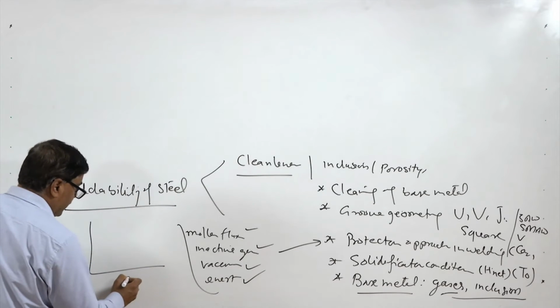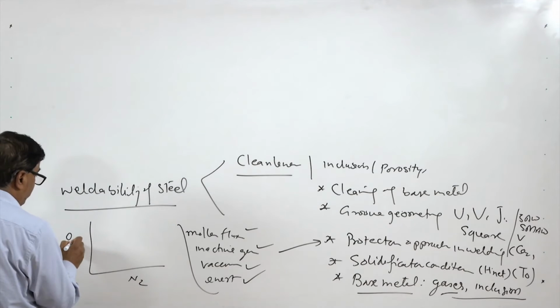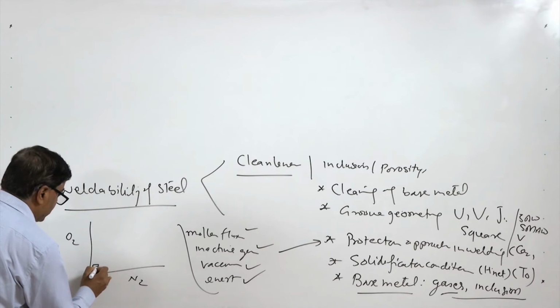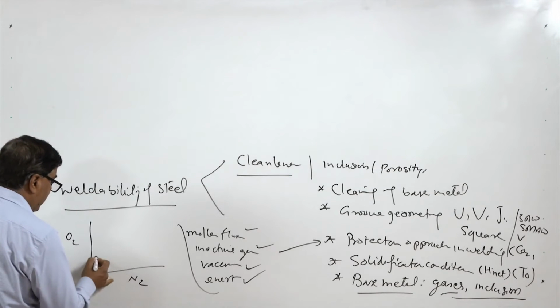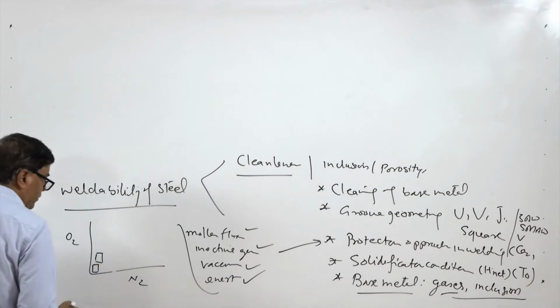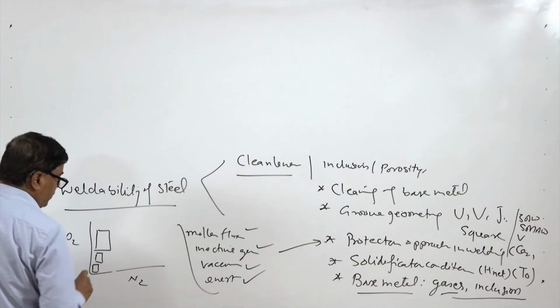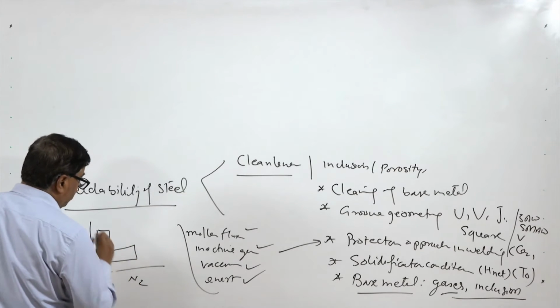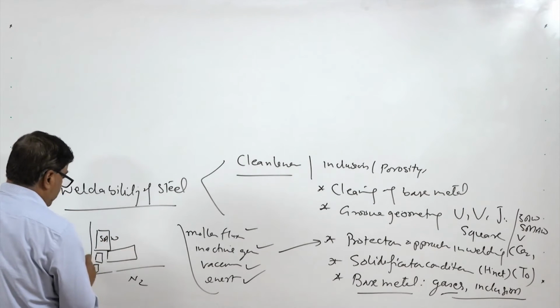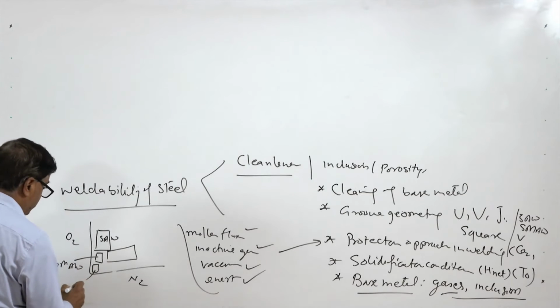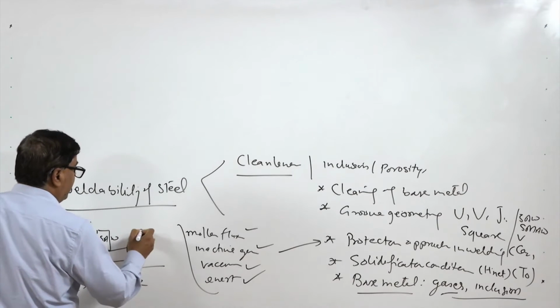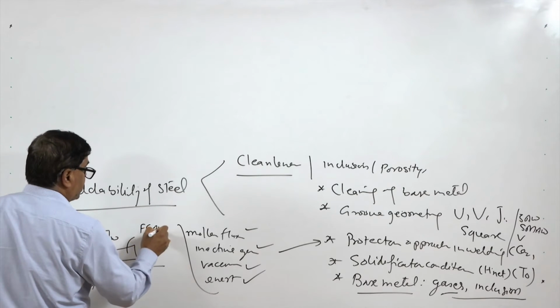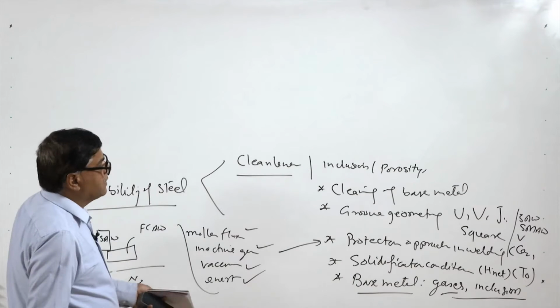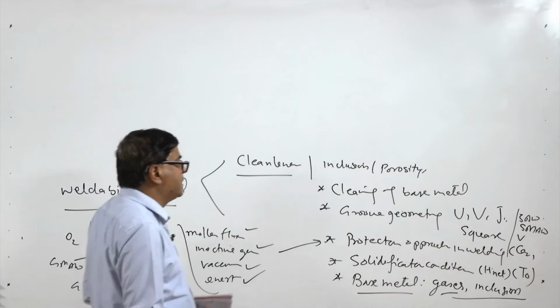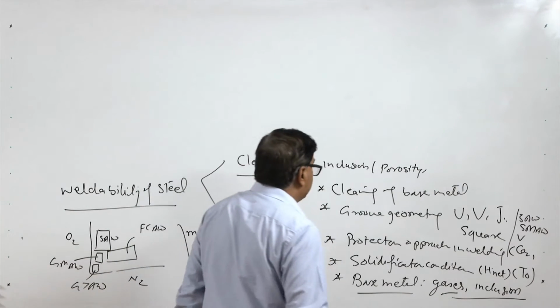produces different amounts of gases in the weld metal, and this we can also see from this typical diagram with nitrogen content on the x axis and oxygen content on the y axis. Here GTAW results in the minimum oxygen and minimum nitrogen, and GMAW results in somewhat greater oxygen and nitrogen. SAW causes a further larger amount of oxygen and nitrogen, and then we see SMAW and self shielded processes like FCAW. Since the protection approach is different in different processes, they result in different oxygen and nitrogen content in the weld metal.